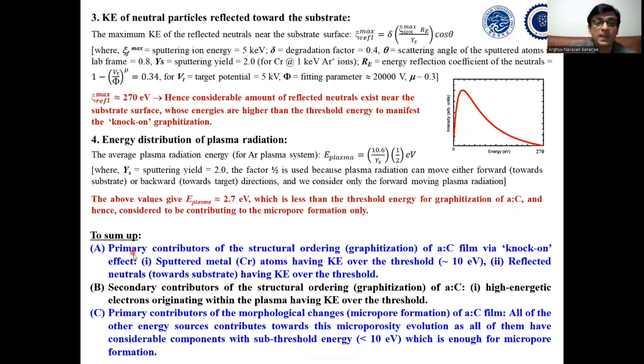Therefore, to sum up, the primary contributor for structural ordering is the sputtered metal atoms having kinetic energy over threshold and reflected neutrals having kinetic energy over the threshold. The secondary contributor for structural ordering is the high energetic electrons originating within the plasma having kinetic energy over the threshold, and the primary contributor for the micropore formation is plasma radiation energy.